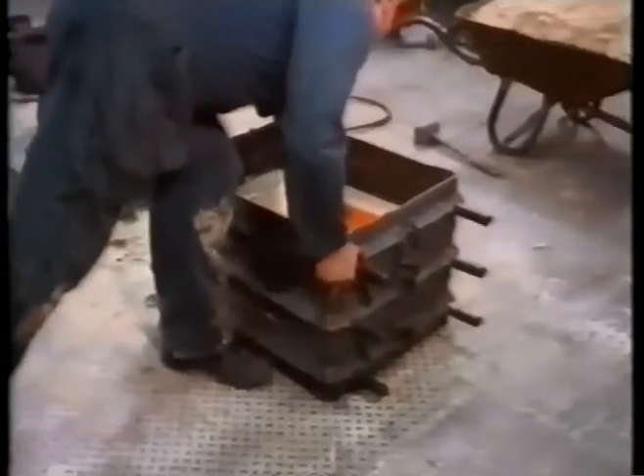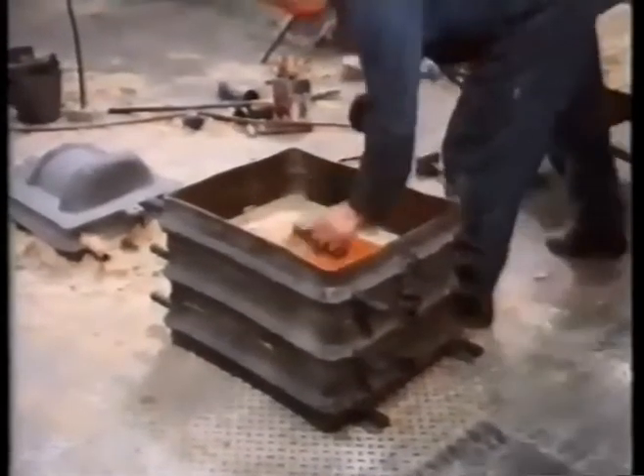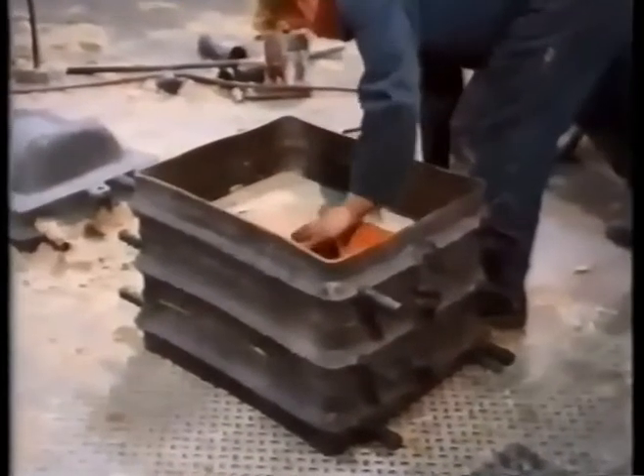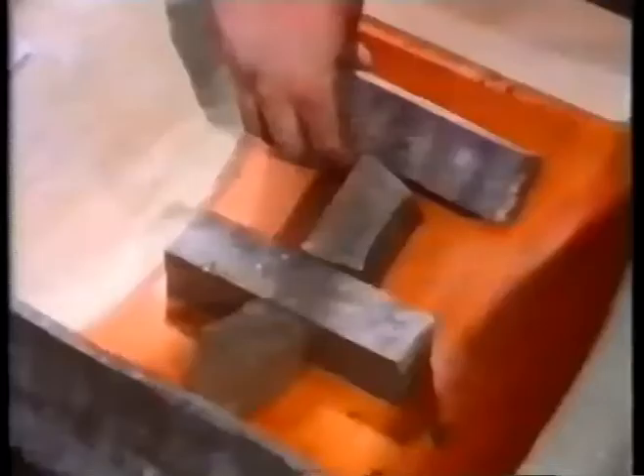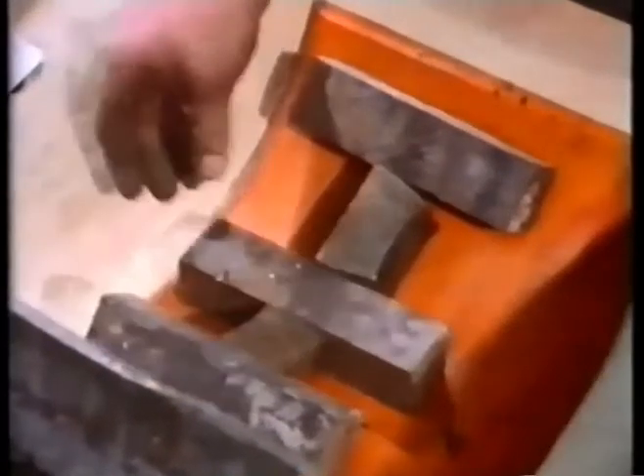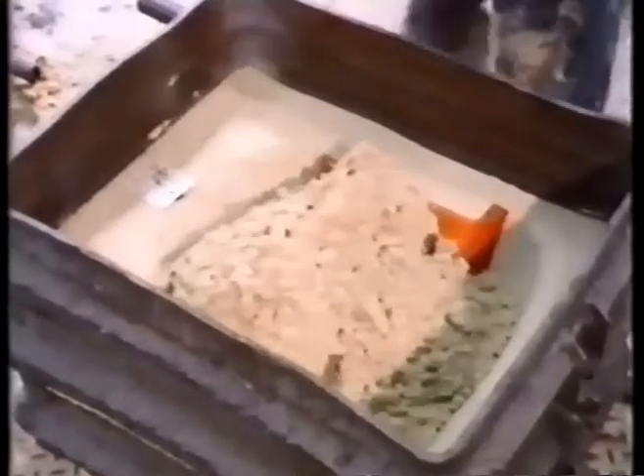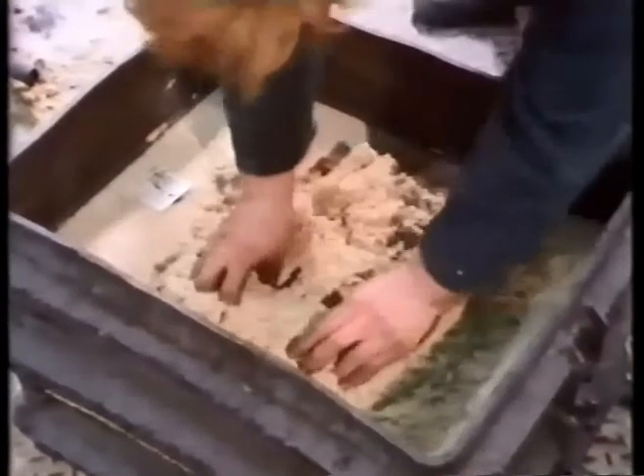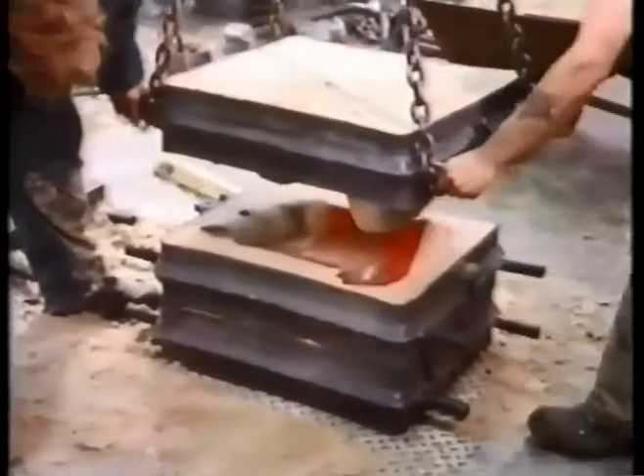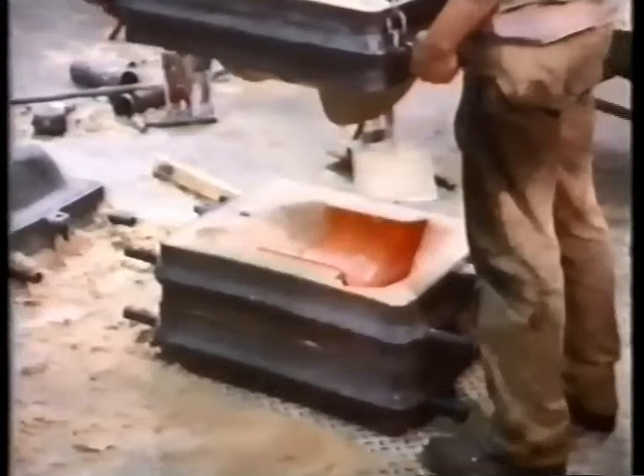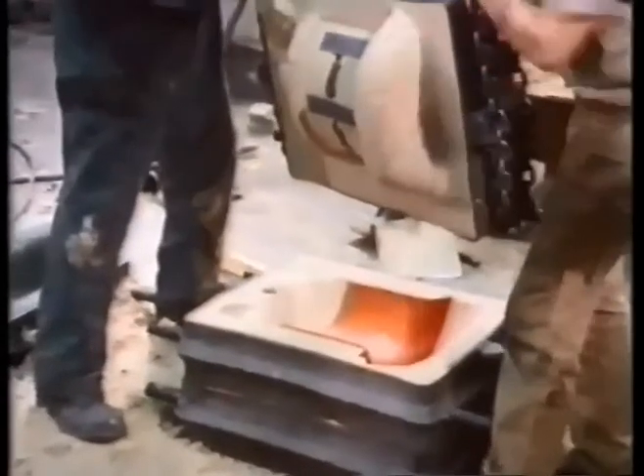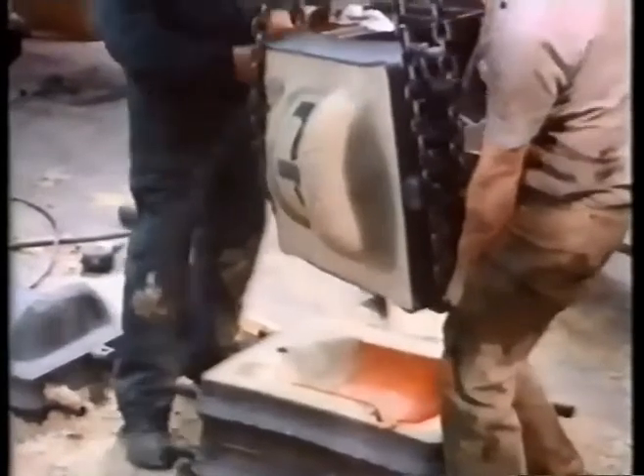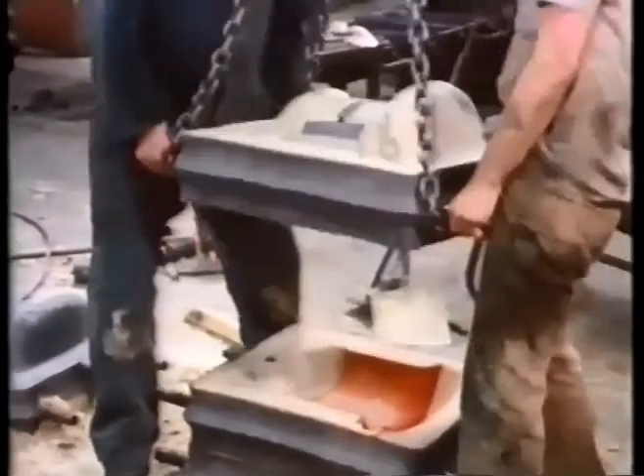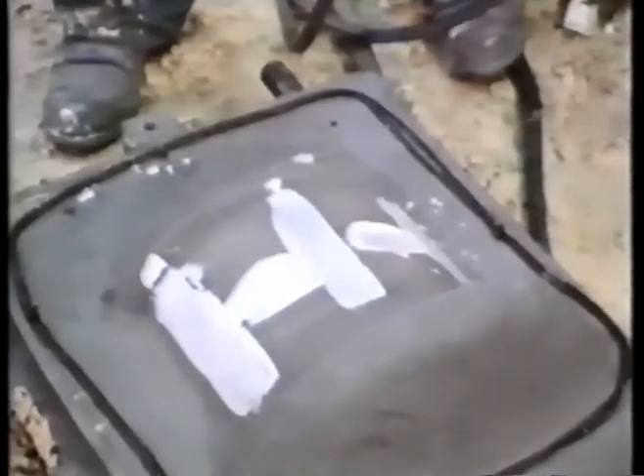Under special circumstances, we can introduce metal chills at an intermediate stage during the manufacture of the sand mould. And these can be placed next to what will be the running surface of the bearing. The rest of the mould is completed as before. The top half of the mould is removed for the mould wash with the metal chills embedded in the hardened sand, ready to chill the metal as it is poured. As well as the usual mould wash, there is also a chill wash, which stops the chill from sticking to the molten metal. The mould is now ready for casting.